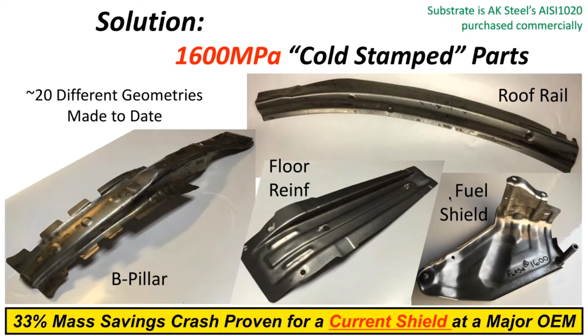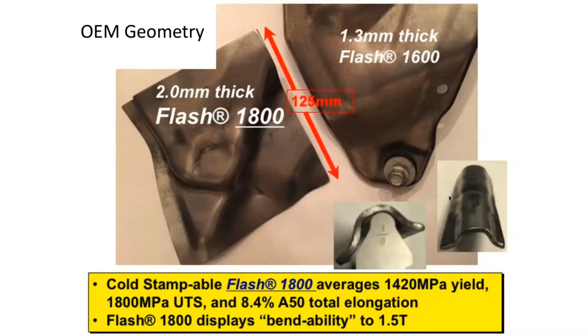The next thing we've done is we took one of the corners of the fuel shield in the lower right inset of the previous slide, and we stamped some 2 millimeter thick 1800 megapascals. This is cold stampable 1800, a 1420 megapascal yield. It's only about 8.5% elongation, but it's got bendability to 1.5 T, which is pretty interesting. We didn't have to roll form it, because with roll forming you can get tighter radiuses. This is actually cold stamping at 1800.